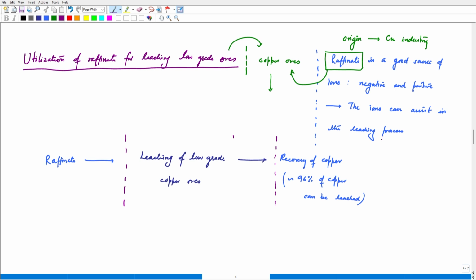So we have taken the raffinate and we leached it with low grade copper ores, and what exactly are we doing? We are bringing this raffinate in contact with the low grade ores, allowing it to react with it and tapping out the leach liquor. So of course it will also lead to the generation of the residual solid, and some amount of copper may still be left in the residual solid, but it has been reported that as high as 96% of copper can be leached.